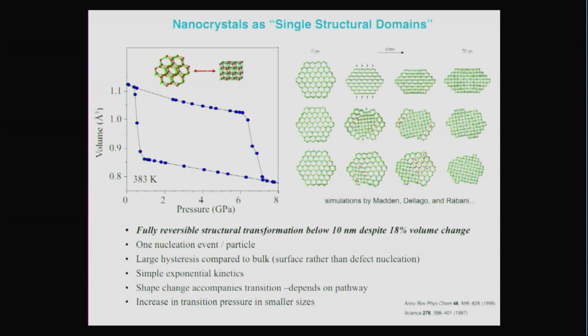Eventually, the transformations do nucleate at the surface of the crystal, which is a type of weak spot. But it turns out, interestingly, most commonly in the types of structural transformations that we were looking at, defects in the bulk material initiate at much higher energy types of grain boundaries and other defects, which are not present in the nanoparticles. And therefore, they show a qualitatively different behavior with respect to that. You can see the perfection of the nanocrystals there.